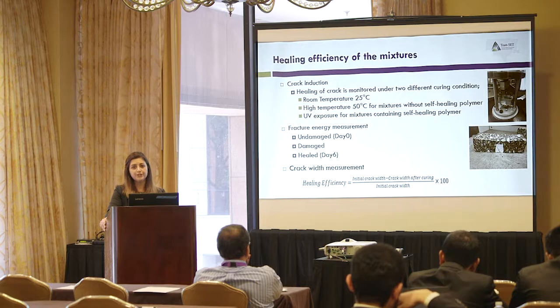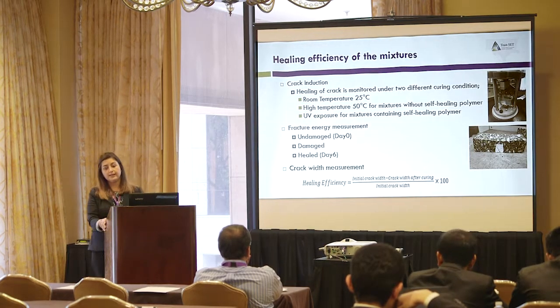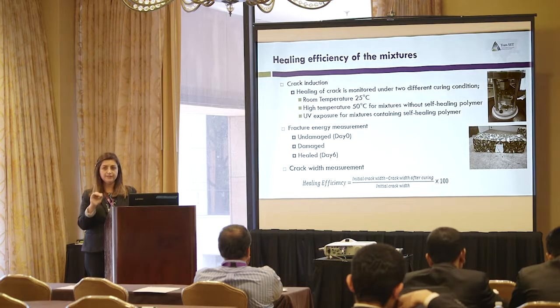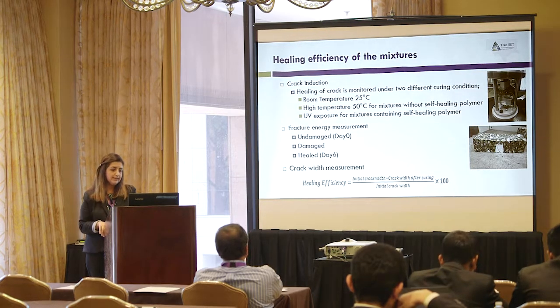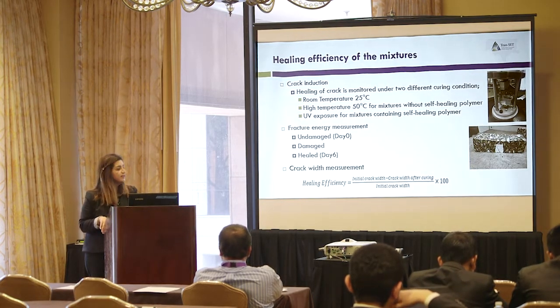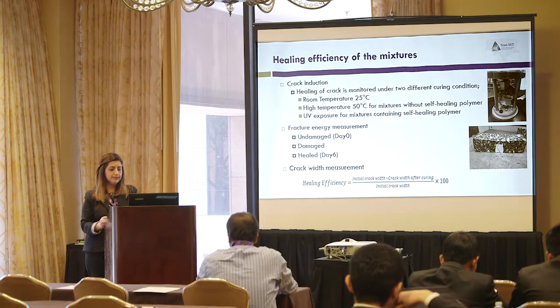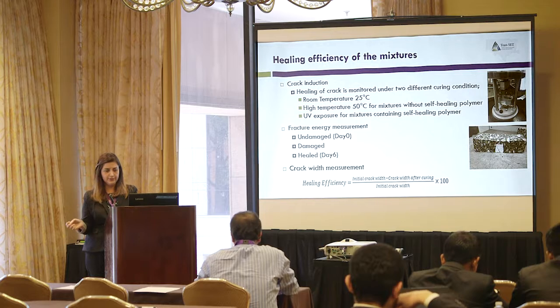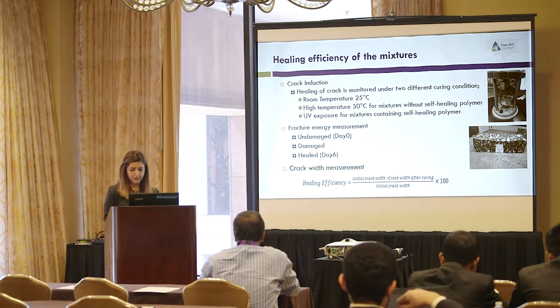We also used crack monitoring. Every day we took pictures of the crack on the bottom of the beam, and then we did an analysis of the width of the crack for each sample, and we defined healing efficiency of the beams as the initial crack width minus the crack width after 6 days of curing, divided by the initial crack width.